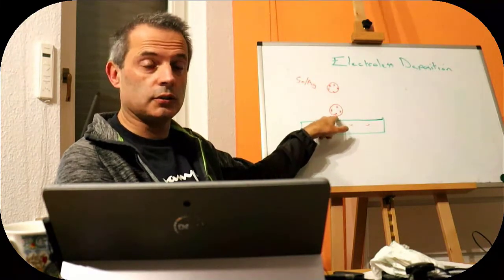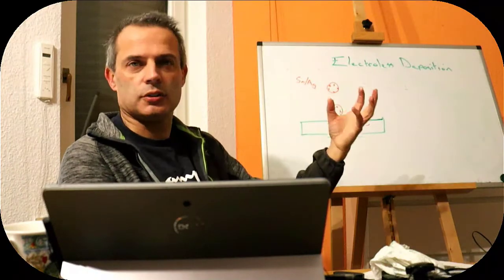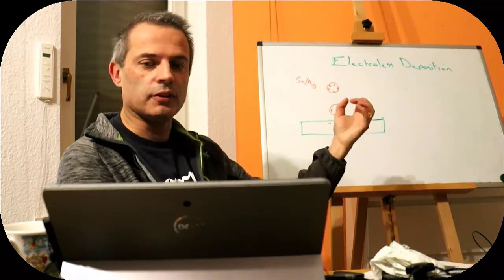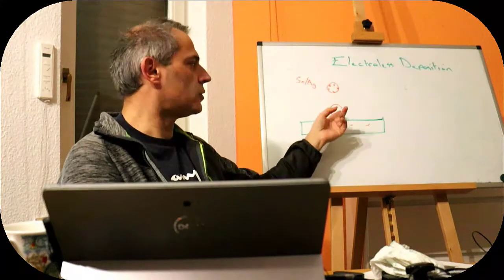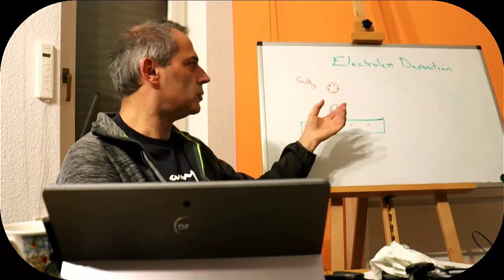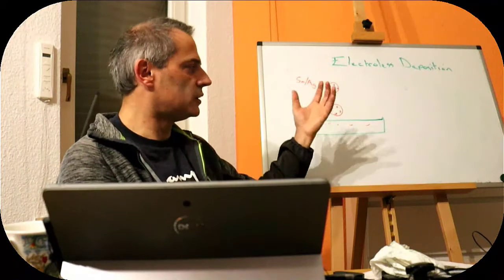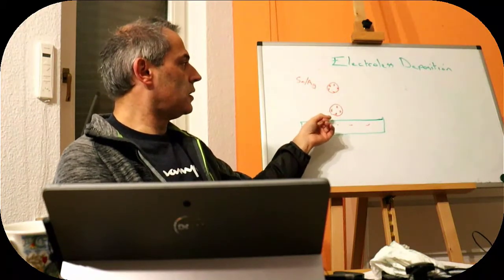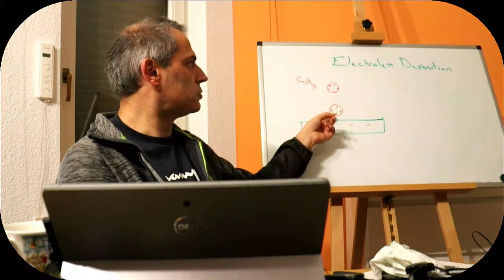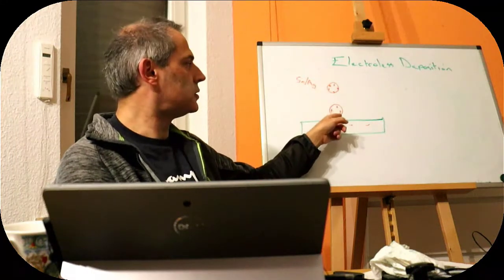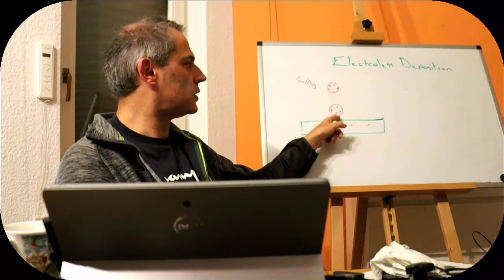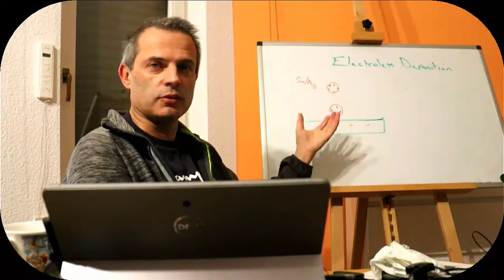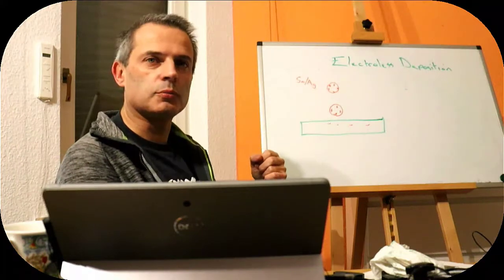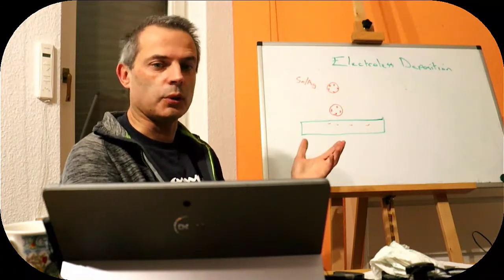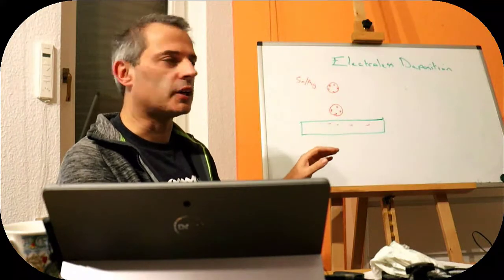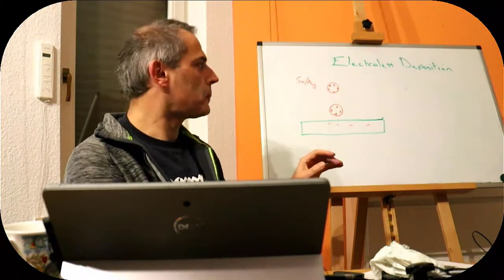There's only a small interaction area, because it's a spherical particle, so there's only one effective point where it's touching, but obviously in reality it won't be quite such a perfect sphere, so it will distort. That's not a problem because we're going to grow copper in this case from the outside of it, and as long as that binds to our surface, our crime of not having a very well attached catalyst particle will be covered up fairly quickly. Then we'll have a metal layer on our surface and everything will be happy.